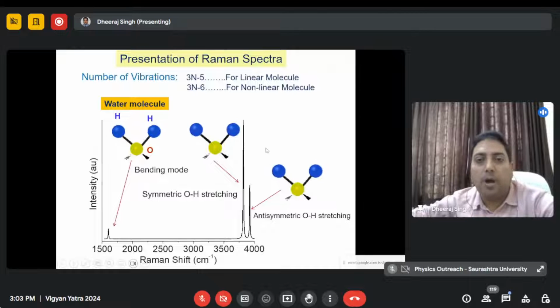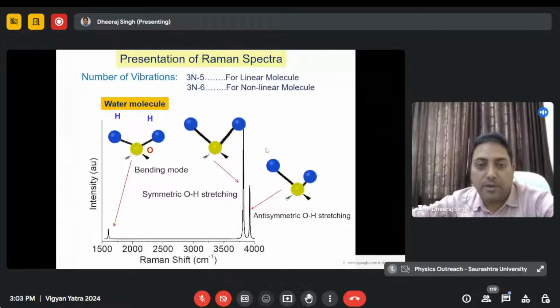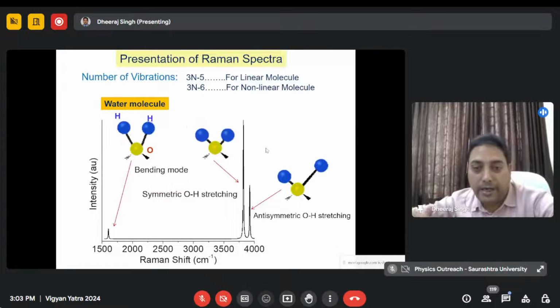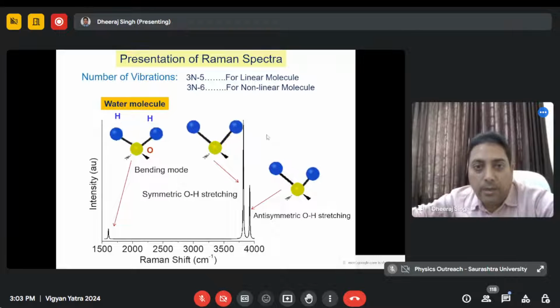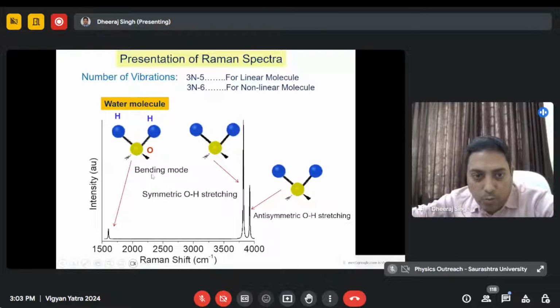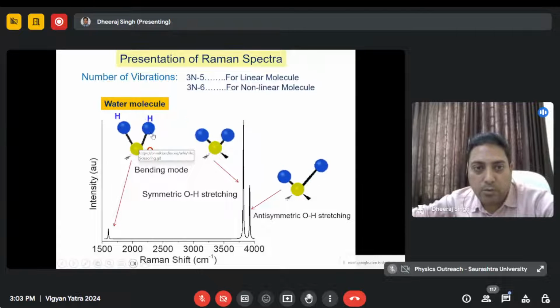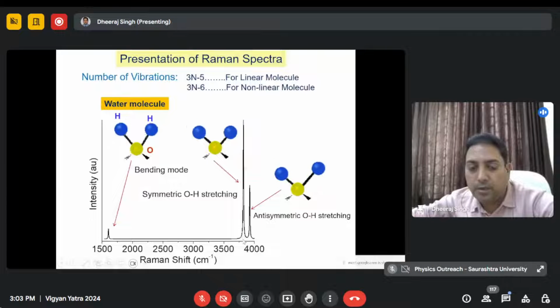And the same vibrations will also be obtained in IR spectroscopy, but with different intensity, because Raman spectroscopy gives similar information. Symmetric stretching is more Raman active, and anti-symmetric stretching is more IR active. Anyway, now this is the Raman spectrum of the water molecule, where we can see that at 1650 centimeter inverse, we are getting a small peak connected to the OH bending mode. And here symmetric OH stretching is coming at around 3800, and anti-symmetric stretching is here. So in any water molecule, if you take Raman and IR, these three frequencies come from OH bending, symmetric OH stretching, and anti-symmetric OH stretching.